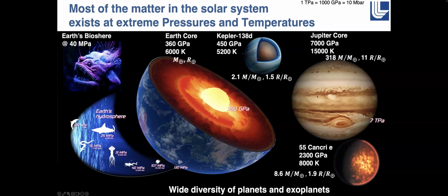We can do X-ray diffraction exceeding the pressures at the cores of Uranus and Neptune, and so it's pretty exciting to be able to actually look at what's inside of planets, and especially large exoplanets where it's very difficult to do seismology or something to try to explore what the centers of those planets look like. And so doing laboratory experiments, both in diamond cells and in dynamic compression, is really important for planetary science in general.